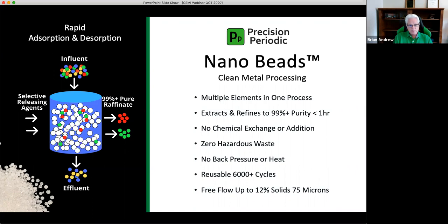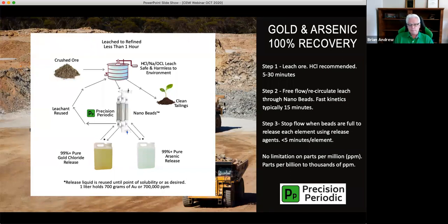And that gives you a very simple process flow. Here's an example of gold. This is a process we have a contract for. In this case, we're cleaning up arsenic as the main thing, but a lot of the arsenic is in arsenical pyrite, left over from 100 years ago mining in parts of America and Canada, where it was unprocessed gold ore. So it still has 8 to 10 parts per million gold, which is very profitable, but it has the arsenic, which is leaching into the ground every time it rains. We have the same problem with mercury overseas. We have a mercury contract. We're pulling mercury out of tailings and also gold.